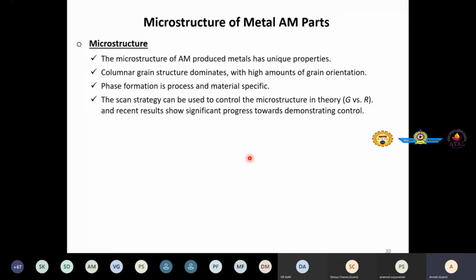More on microstructure of metal AM parts. The microstructure of AM produced metal has unique properties. For example, it has fine columnar grain structure, and we have high amounts of grain orientation. Phase formation will take place, different intermetallic phases and so on. It depends on the process and the material which you are using. The scan strategy can be used to control the microstructure in theory. For example, we can control the temperature gradient versus cooling rate or solidification rate, and we could obtain several kinds of microstructure starting from planar growth to cellular growth to columnar growth to equiaxed growth. So this last aspect is a lot of focus currently, how to obtain cellular growth or equiaxed grain growth. If we produce equiaxed grains, then the advantage would be that the anisotropy we are obtaining can be minimized.